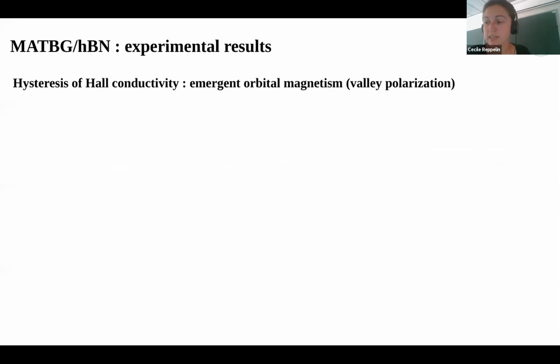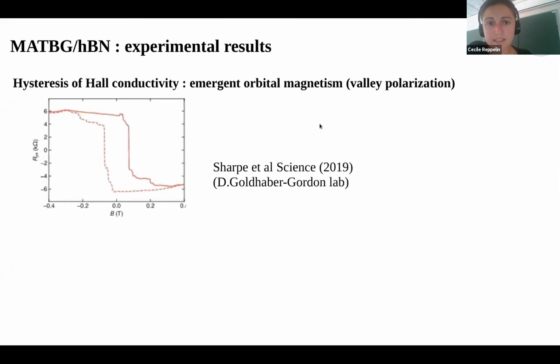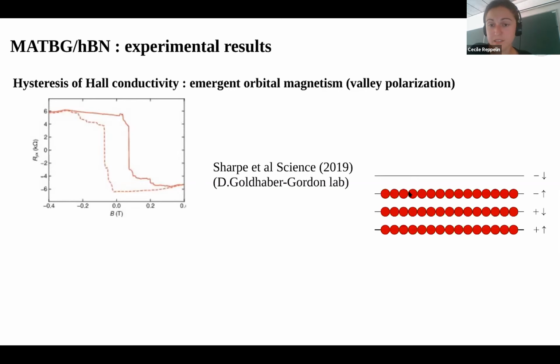So let me start with a few experimental facts. Magic angle twisted bilayer graphene aligned with hBN has been realized before, and this is what is seen in various experiments. So first of all, there's a hysteresis of the Hall conductivity of magnetotransport in general. And this hysteresis indicates an emergent orbital magnetism. This data is from David Goldhaber-Gordon's group, and this was the first time that this emergent orbital magnetism was found, and it was found for filling 3, meaning that in mean field this would correspond to, in the conduction band, filling those 3 bands out of 4.